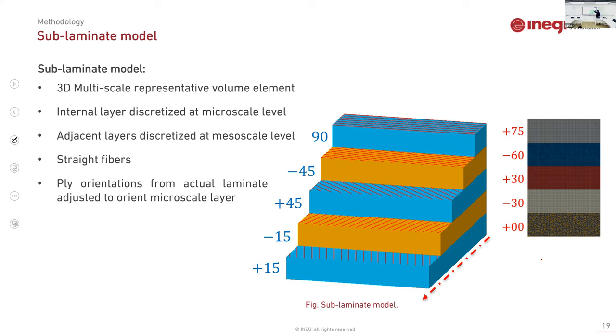What is a sublaminate model? Considering the same layout that is used for the pressure vessel, I have extracted the ply stack layout. Okay, so I have considered the internal layers discretized at microscale level. It means that the fibers and resin are discretized separately, and the other adjacent layers are discretized considering the homogenized material. Okay, this portion of this lamina has a micromechanical model discretization. The other adjacent layers have a homogenized layer model. This model is 3D. You can see in the design. Okay, this is an important thing. These are the actual orientations of the vessel. I have rotated it to facilitate interpretation to 0 degrees in the internal layer.